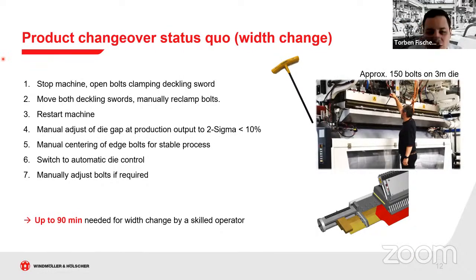Then normally you restart the machine, and then you manually go with the Allen key over the die. This is approximately 150 bolts on the 3-meter die, and you manually adjust the melt flow by torquing the bolts. And then you look, where does my melt flow? How good is my production quality? And then you iterate until you reach a certain level of production output where you say, okay, this is kind of good quality. And even this process takes up to 30 to 40 minutes.